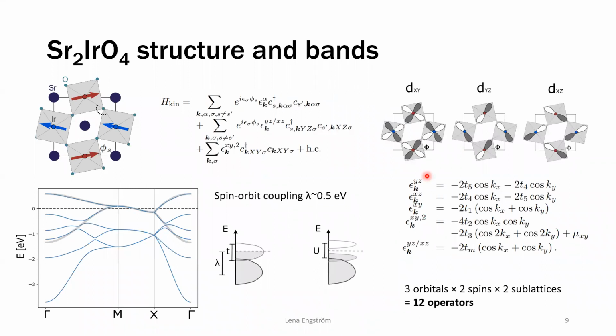So for this strontium 2 iridium oxide 4, we do have this sort of square lattice symmetry that I described earlier. Here we sort of have these iridium sites that are surrounded by these oxygen octahedra. A difference from the cuprate is that these are actually rotated with a much bigger angle, and that the magnetic moment in the ground state seems to follow this rotation much more strongly. And the full model, before we add interactions here, we want to consider 3 different orbitals. So these are, due to crystal field splitting, these 3 d orbitals that arise close to the Fermi surface.